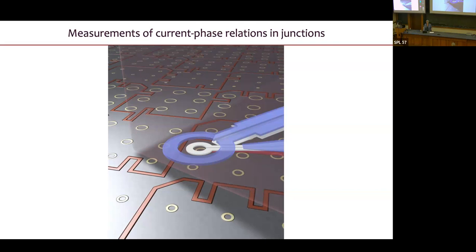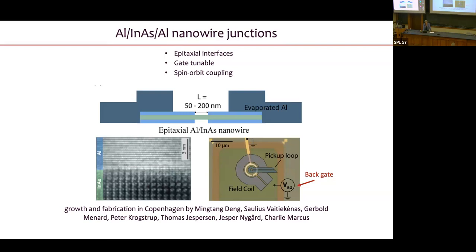Okay, so the particular samples that I want to tell you about that we've studied quite a bit for the last 7 years actually are these aluminum indium arsenide aluminum nanowire junctions. They're actually very studied because they have spin orbit coupling, which is important for Majoranas, but not important for what I'm going to show you here at all. So just ignore that. The main thing that we like about them is that they have these very beautiful epitaxial interfaces, just very, very clean materials. And also the indium arsenide is a semiconductor and is gate tunable.